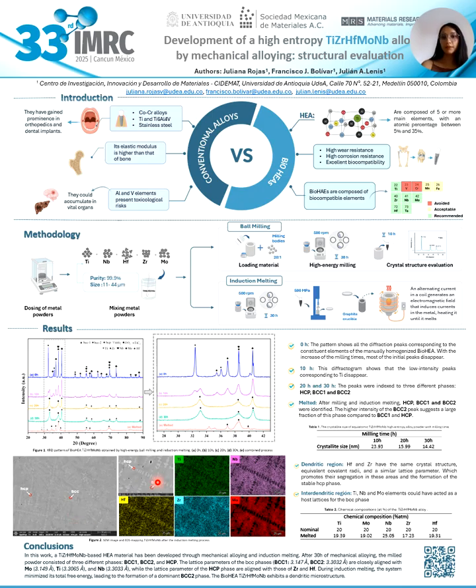The elemental mapping shows that titanium, zirconium, and hafnium are uniformly distributed across the sample. However, zirconium and hafnium exhibit microsegregation in the dendritic regions. On the other hand, molybdenum and niobium show clear segregation in interdendritic regions. Also, the chemical composition results indicate a composition close to equiatomic.